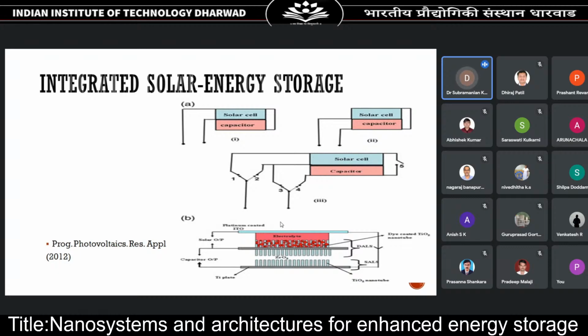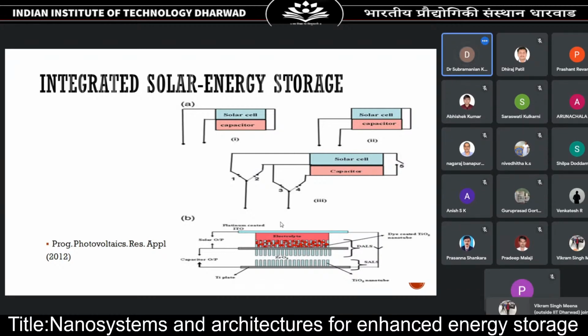But you can also see that on the other side of the titanium plate, the titania nanotubes are extending on both sides. And there is a thin layer of zirconium dioxide, which is a dielectric material. So the other side of the titanium plate functions like a capacitor, which can store charge. And because it shares a common interface, the charges can flow seamlessly from the solar cell to the capacitor. So this is an integrated solar and energy storage device realized through double anodization of the titanium plate.